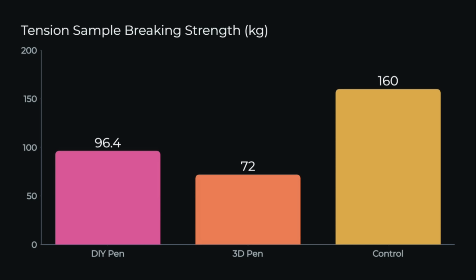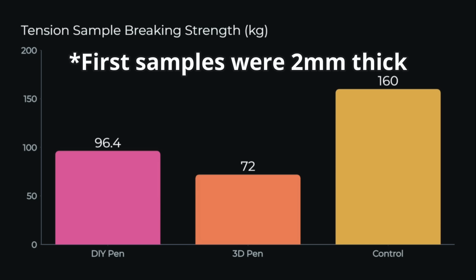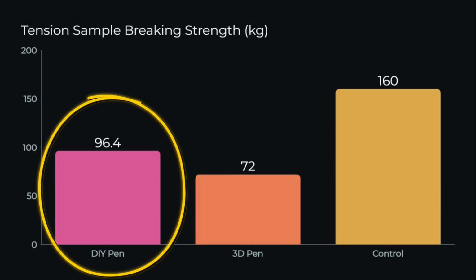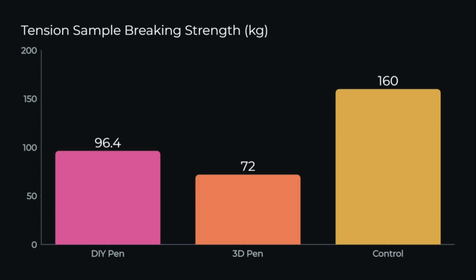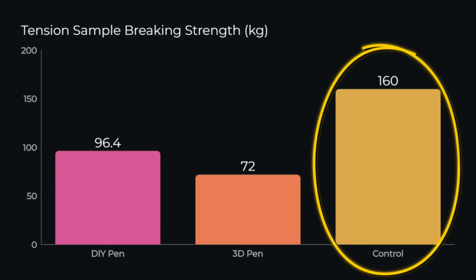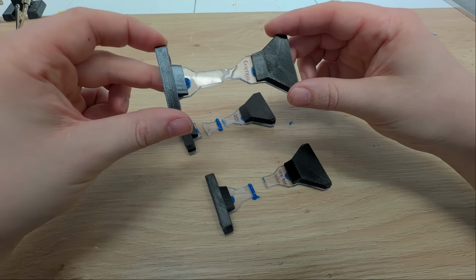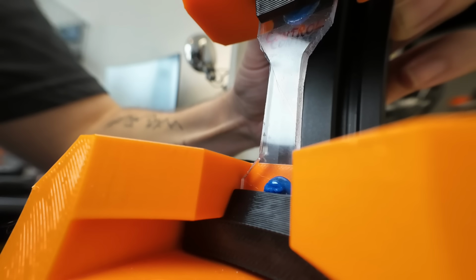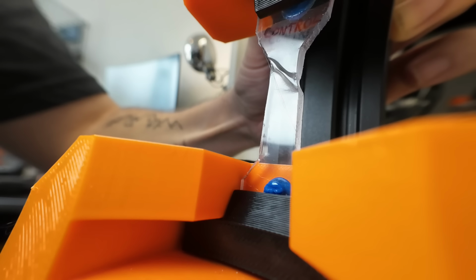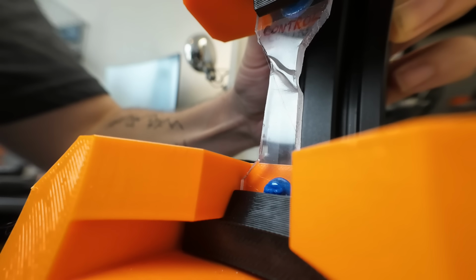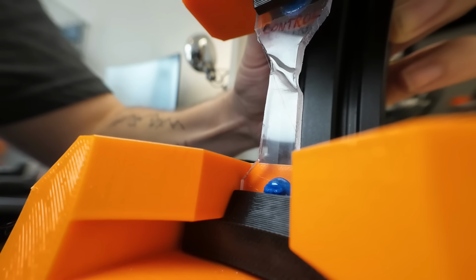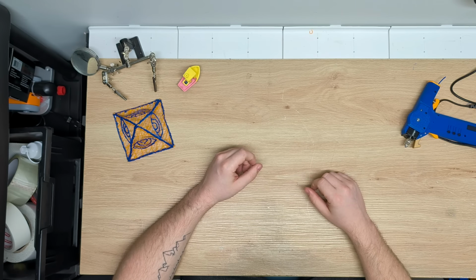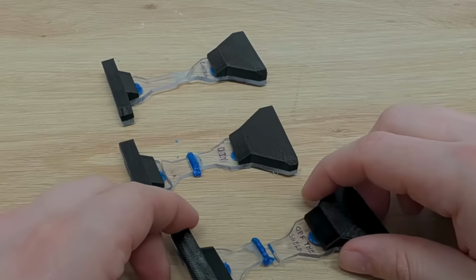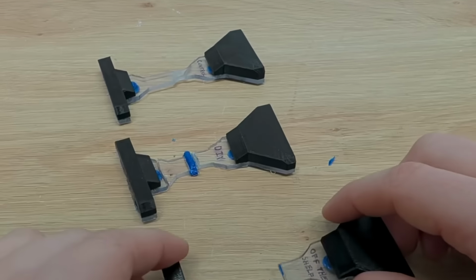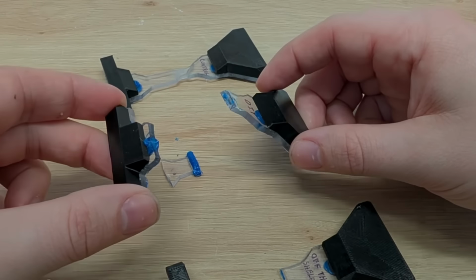And this time we can see that, at least for the thicker 3mm samples, our DIY pen does make a stronger weld. Unsurprisingly, the unwelded control sample was the strongest, but interestingly, it was the only sample not to really break. Instead, it kind of yielded at 160 kilograms, basically started to stretch thin. It also had quite a bit more strength than both our welded samples. Both our welded samples again broke at the weld location this time, but interestingly our sample welded with our DIY pen had an additional fracture in the actual base material near the bottom.